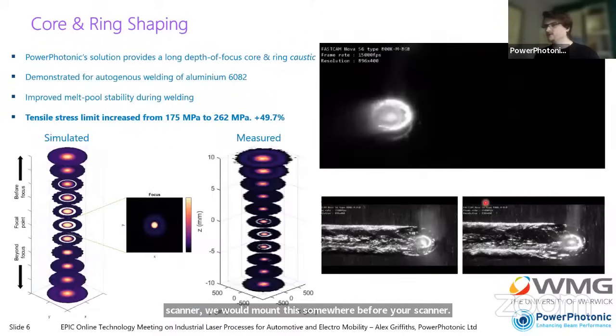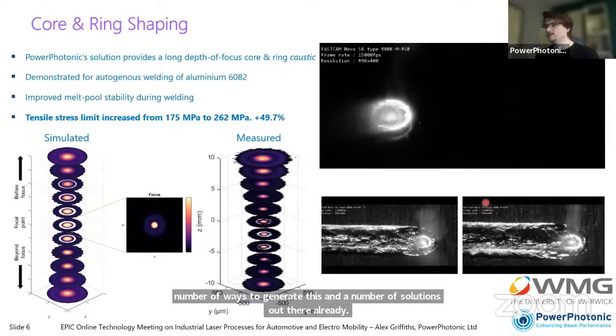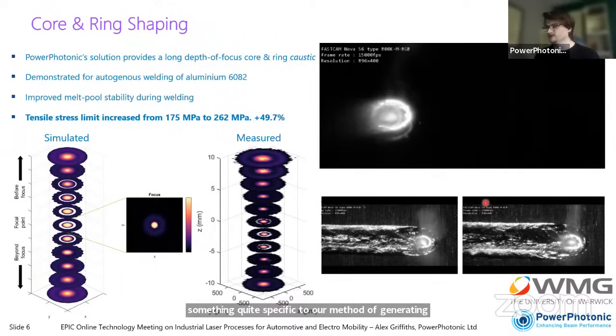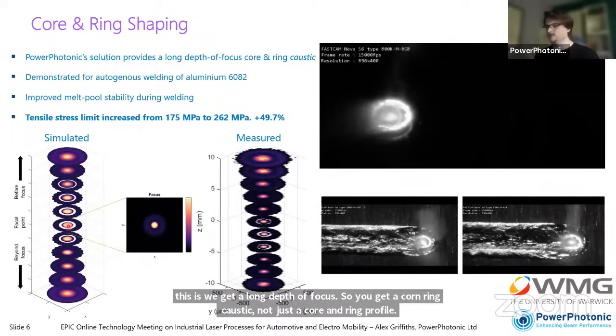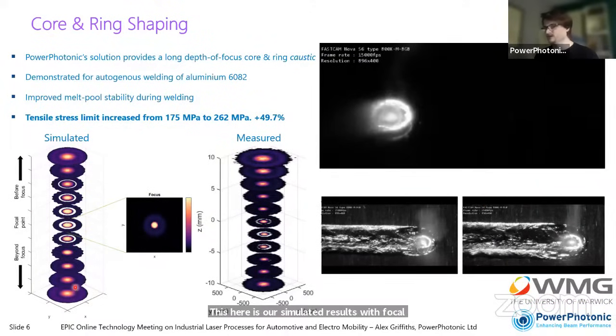So moving on to some actual beam shapes, the core and ring shape is becoming quite commonplace. There's a number of ways to generate this and a number of solutions out there already. Something quite specific to our method of generating this is we get a long depth of focus. So you get a core and ring caustic, not just a core and ring profile. This here is our simulated results with focal position in the middle. Before focus and after focus, that core and ring is maintained. And then we have a measured version here as well. So we get good agreement between simulation and measurement.